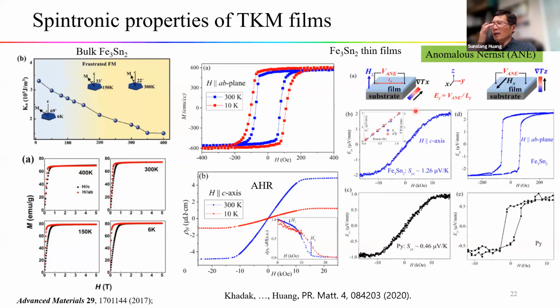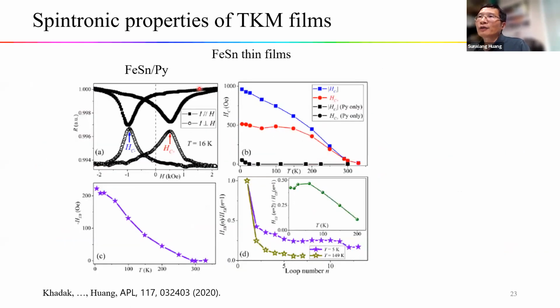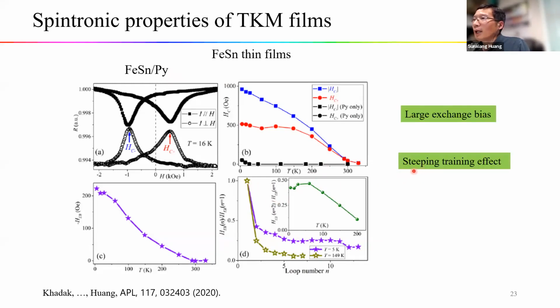We also did an anomalous Nernst measurement, which probes the Berry curvature near the Fermi energy. It shows the samples have a large anomalous Nernst effect, which may also arise from the Weyl nodes near the Fermi energy. For the antiferromagnetic one, we can confirm it is antiferromagnetic, and there is also a large training effect, or exchange bias, indicating that in the same film there are multiple equivalent magnetic domains.